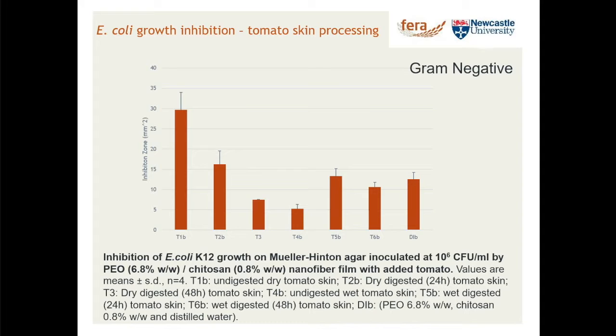Interestingly, if we used dried material and processed it, we got a big effect. If we had wet, raw tomato skins and then chemically processed it, we got actually a reduction in effect. So we're not quite sure why, but it certainly is interesting that we can get an enhanced effect by including our tomato skins. So it kind of indicates there's some value in exploring this further.